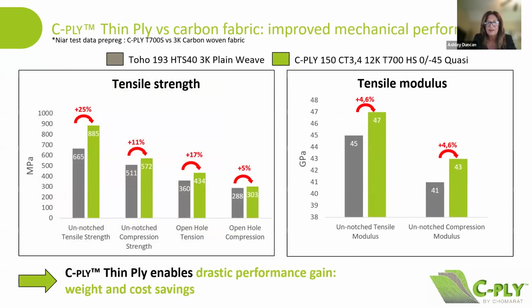So I've done quite a comparison, comparing C-ply with traditional 3K woven fabrics a couple times in this presentation, and not to pick on woven fabrics because we produce those too, but here's another slide that compares the mechanical performance of a C-ply thin ply laminate against a traditional 3K plain weave woven fabric. In this study, 150 GSM C-ply using a 12K T700 was used. The 3K fabric is represented by the gray bar, while C-ply is represented by the green bar.